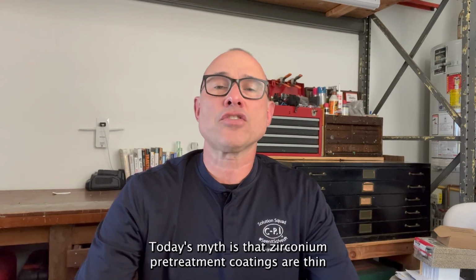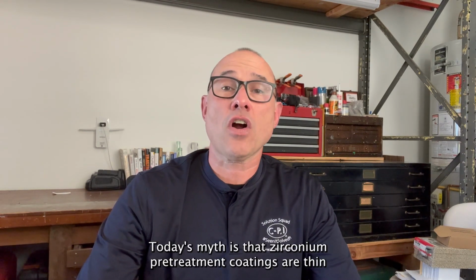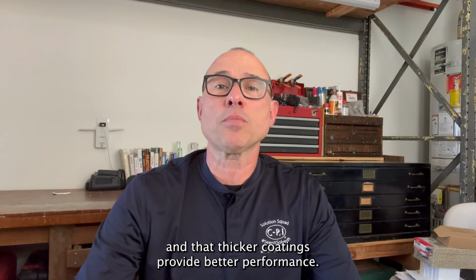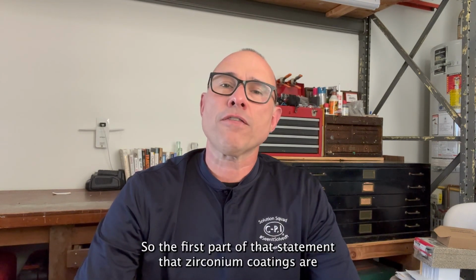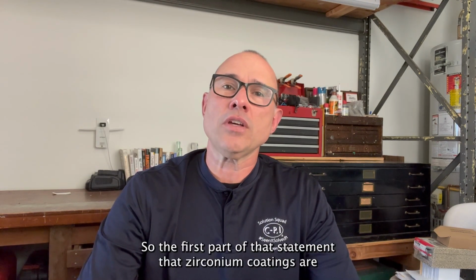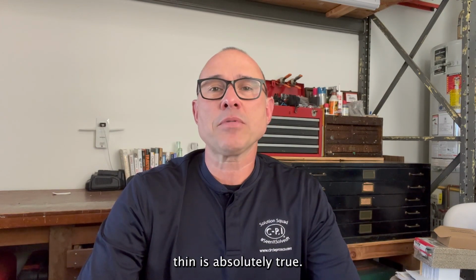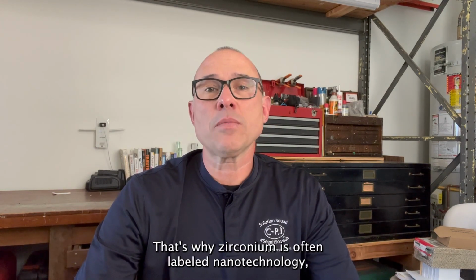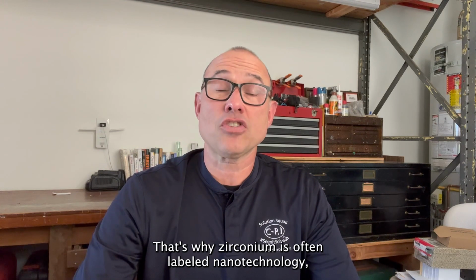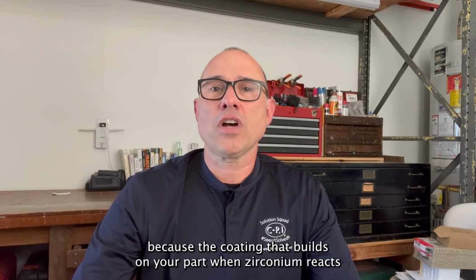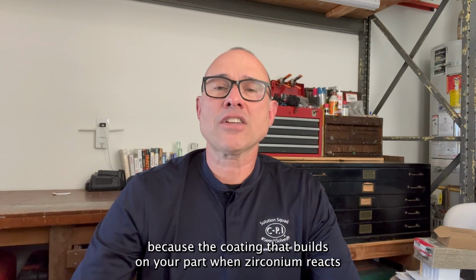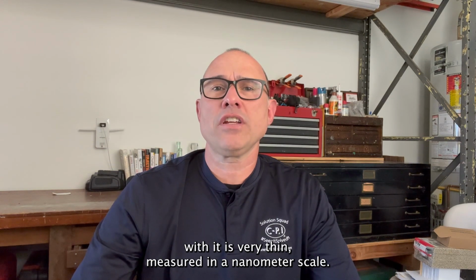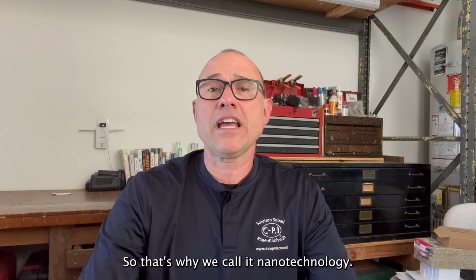Today's myth is that zirconium pretreatment coatings are thin and that thicker coatings provide better performance. So the first part of that statement, that zirconium coatings are thin, is absolutely true. That's why zirconium is often labeled nanotechnology, because the coating that builds on your part when zirconium reacts with it is very thin, measured in a nanometer scale. So that's why we call it nanotechnology.